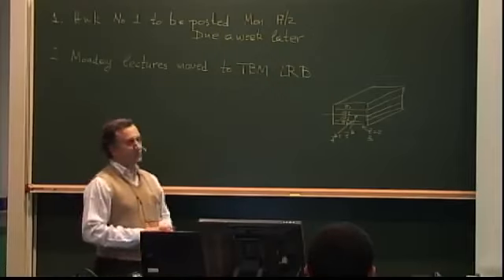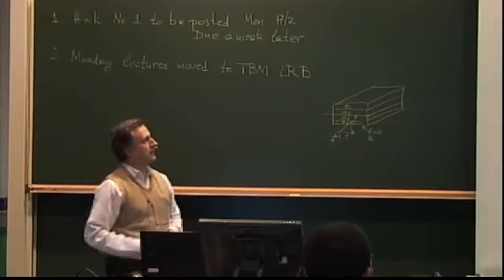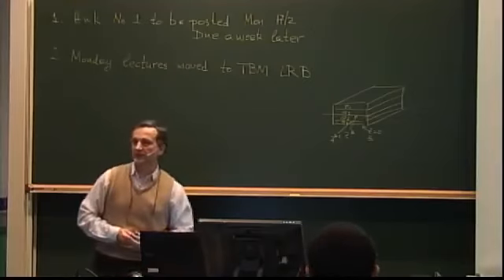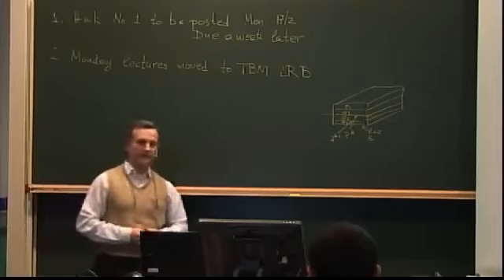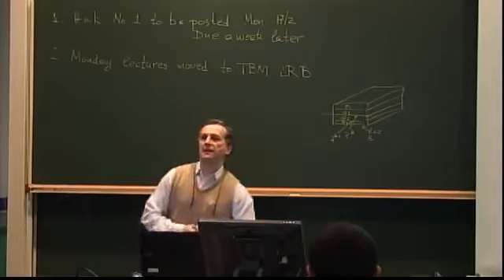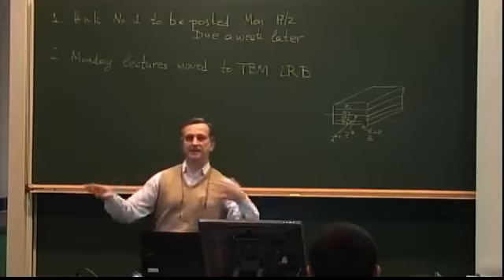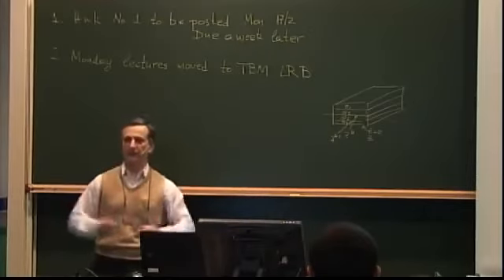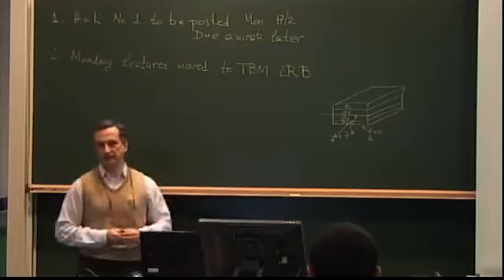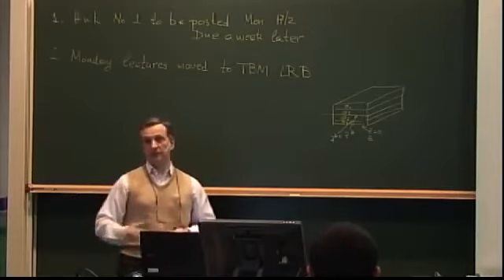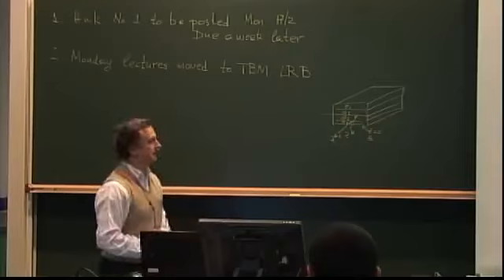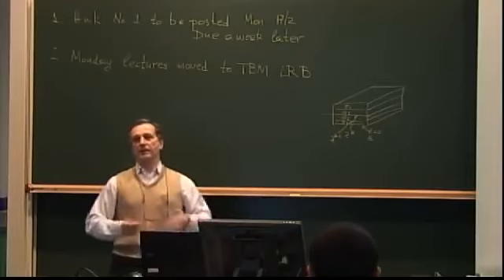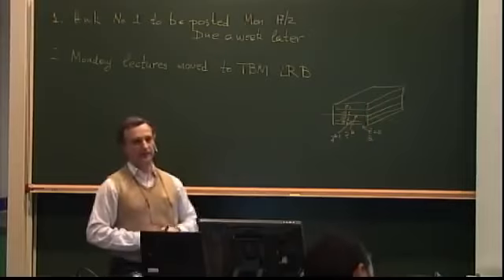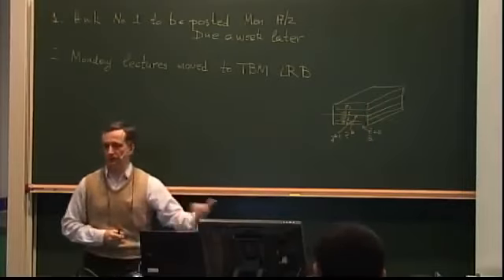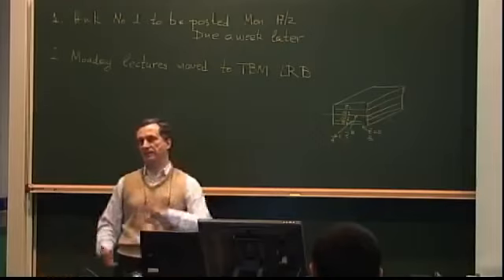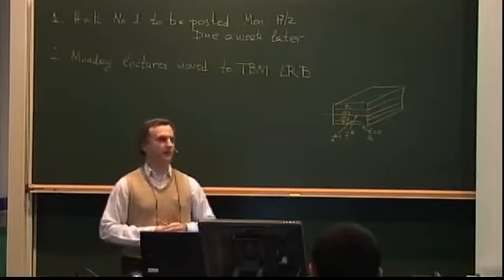So all you do is go back to your linear algebra and take this huge matrix and invert it. Or you ask MATLAB to do it, and I invite you to try that with a good size laminate, not 0/90, but something complicated. In most cases, it can't invert it. Not that it's not doable, it's just that numerically it becomes quite difficult. I've had a student doing that in general, and it was a nightmare. And of course, you cannot do symbolic manipulation. In Maple, it's a 6 by 6 matrix, and you get 60 pages for each term.